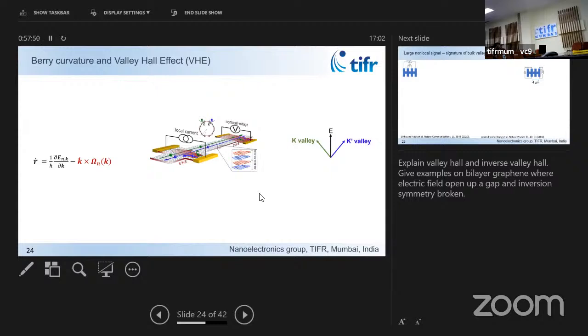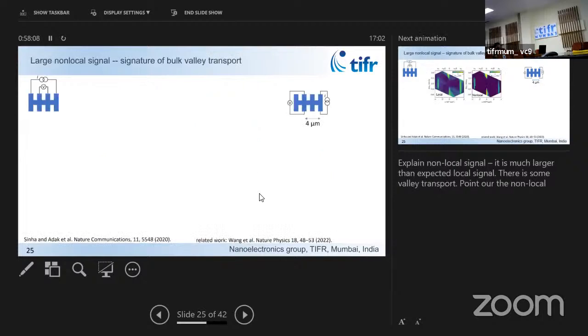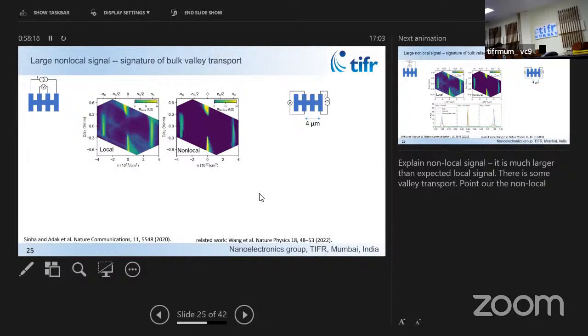When the valley current flows, it also gives rise to the opposite, inverse effect, which is called the inverse valley Hall effect. Because you're sending a pure valley current in this direction, because of the Berry curvature, it will generate a voltage, which is a way to detect the presence of the Berry curvature. And that's what we did, and we showed that this Berry curvature is tunable with electric field. For that, we do experiments in two main geometries.